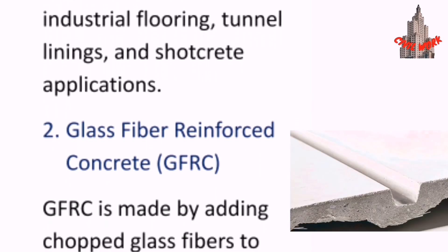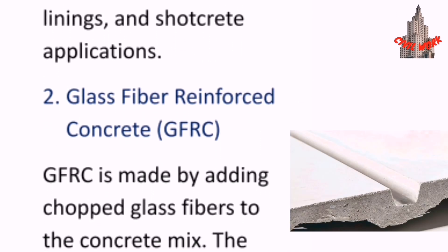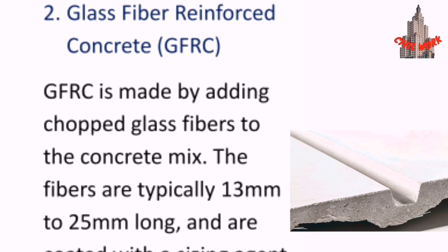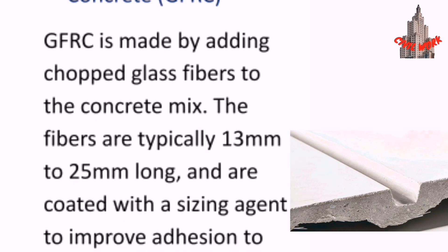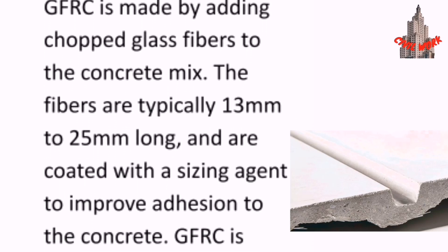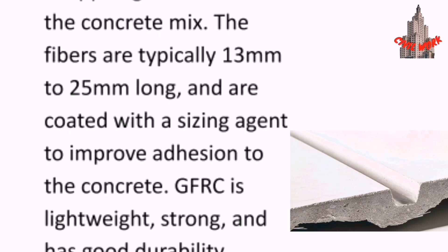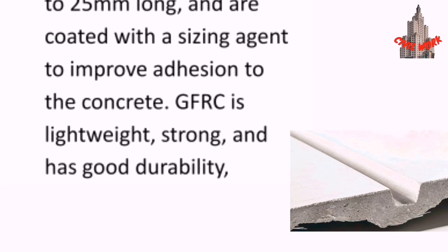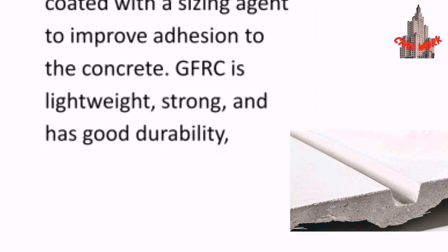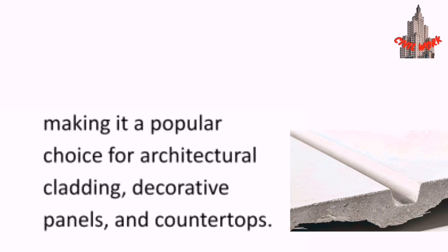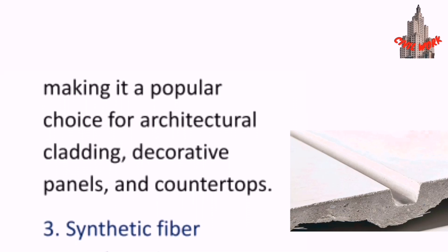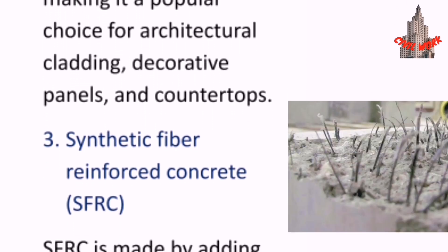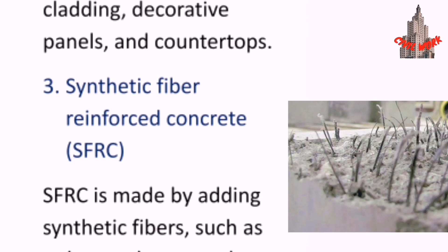Glass fiber-reinforced concrete is made by adding chopped glass fibers to the concrete mix. The fibers are typically 13 mm to 25 mm long and are coated with a sizing agent to improve adhesion to the concrete. Glass fiber-reinforced concrete is lightweight, strong, and has good durability, making it a popular choice for architectural cladding, decorative panels, and countertops.